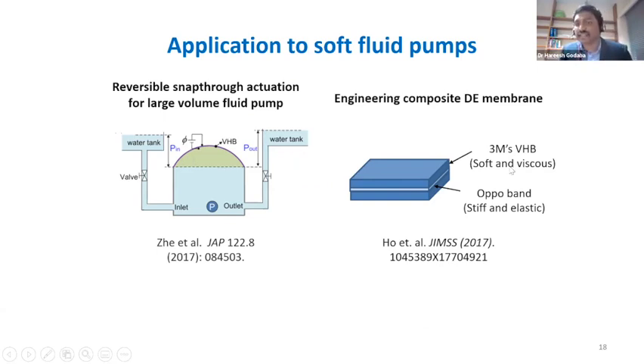However, this material has high viscoelasticity, or it is highly viscous in nature, so the hysteresis and energy dissipation is high. But for a fluid pump, we would want reasonably higher actuation speed. So we engineered a composite dielectric elastomer membrane where we combine the soft and slightly viscous 3M's VHB with a stiff and elastic band from a company called Oppo, which is the band people use for physiotherapy. Once we combine these two together, we are able to tune the resonant frequency of this pump to achieve significantly higher flow rate as compared to just 3M's VHB.